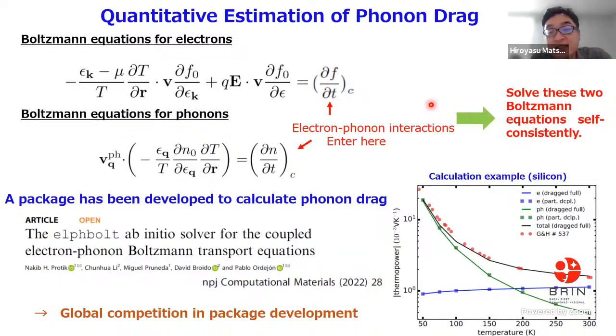Recently there is a package to calculate the phonon drag contribution. This is called elphbolt. This is not my study, maybe a US group. Anyway, recently many groups are trying to calculate the phonon drag contribution by using band calculations combined with Boltzmann equations. Maybe this is global competition in package development. So this is the theoretical result for the silicon case by using this package. The red point is the experimental result and the black one is the theoretical result. Very consistent with the experimental result.